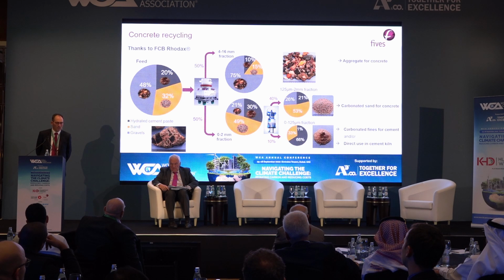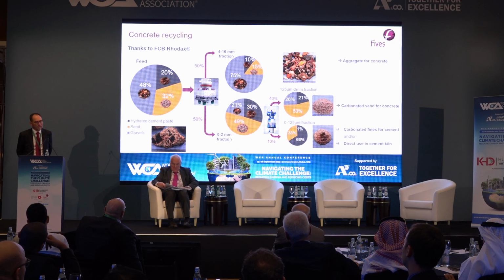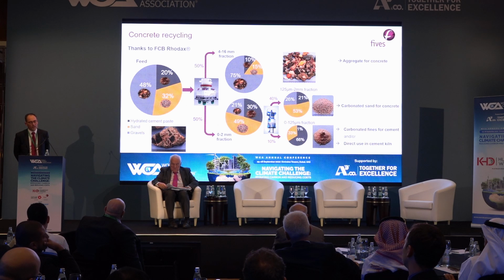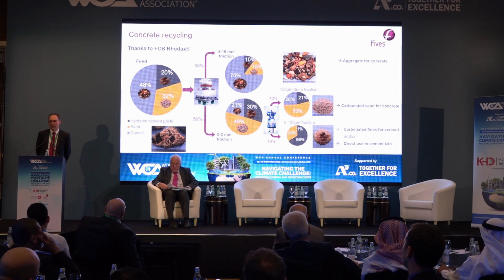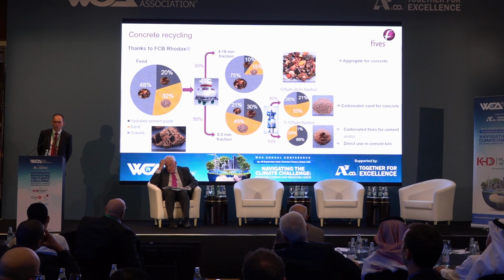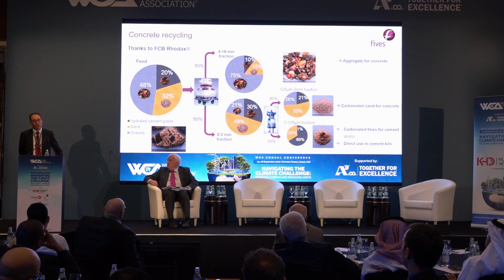So this application of this crusher, which was originally for very hard and very abrasive material in the mineral industry, it is used to grind silicon metal, to grind titanium slag, is also applicable here, and it is very virtuous because you have 100% recycling of concrete, and you can use this material either in your process or in CO2 absorption as a carbon sink. And all these technologies are available, already used for decades, but just recently applied to the cement industry.